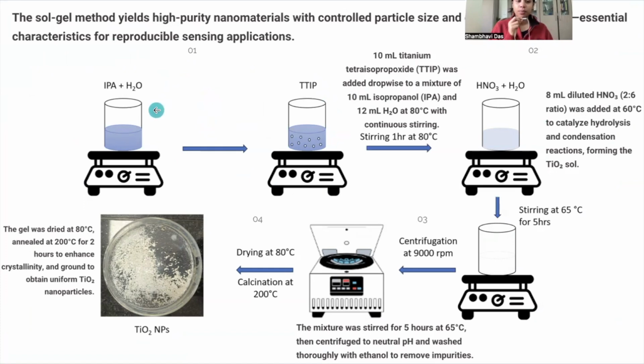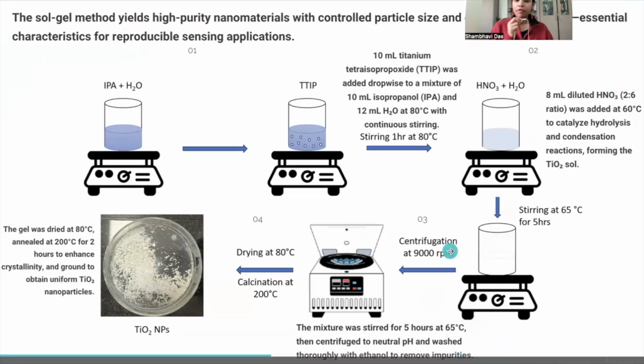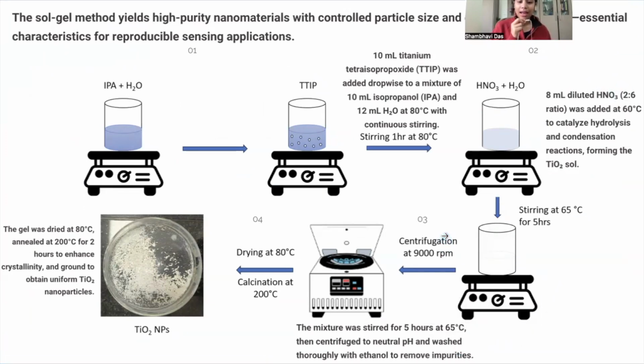We first added isopropanol and water, to which we then added titanium tetraisopropoxide dropwise to the solution at 80 degrees Celsius. This was then left to stir at constant temperature for an hour. After an hour, we then added nitric acid after lowering the temperature to 60 to 65 degrees Celsius. This was then left to stir for about 5 more hours for the gel and the nanoparticle formation. After 5 hours, it was then centrifuged at 9,000 rpm and washed with first water then ethanol to remove the impurities. It was then dried at 80 degrees Celsius and calcinated at 200 degrees Celsius,